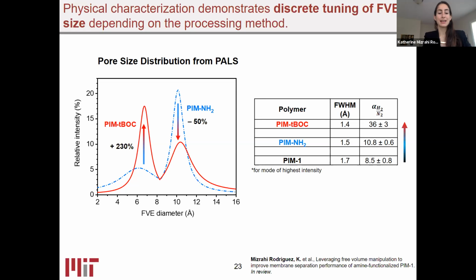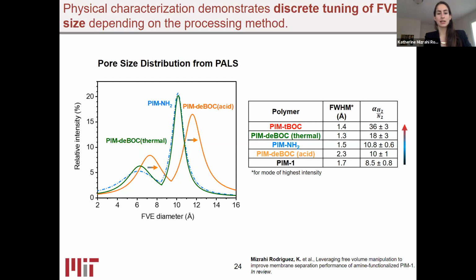When the TBOC group is added, there's actually a shift in the complete landscape of porosity in the sample, where there's a boost in the amount of small pores. Both the amount as well as the average size decrease significantly, and this again results in a boost in selectivity for hydrogen over nitrogen. Now, when the samples are deprotected, we find that the acid deprotected sample shows an increase in the average free volume element diameter, which indicates that our hypothesis of swelling of the material during acid deprotection was correct. This can result in increased permeabilities, but not so much of an improvement in selectivity. Finally, the thermally deprotected sample shows a narrowing of the free volume distribution, which we think accounts for the improvement in selectivity that we found. For this to happen, we believe that simultaneous deprotection as well as in situ cross-linking need to take place.